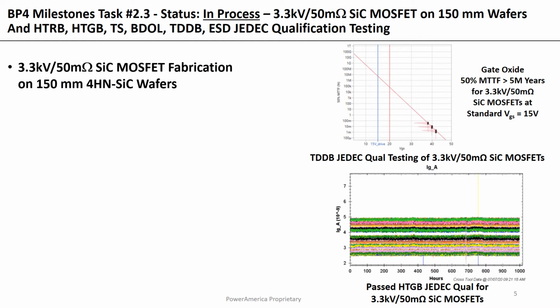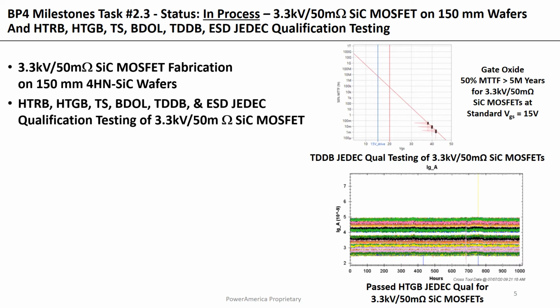In terms of BP4, there are two major groups of activities. The first is 3.3 kV silicon carbide MOSFET fabrication on 150 millimeter silicon carbide wafers, and then JEDEC qualification of 3.3 kV 50 milliohm silicon carbide MOSFETs, including HTRB, HTGB, thermal shock, body diode, operating lifetime, TDDB, and ESD.